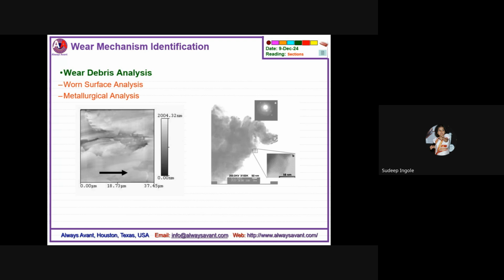The scale of this particular image on the left hand side is around 37 micron. You can see that 37 micron is a pretty small scale, and this image was taken by atomic force microscope, scanning a very small surface, whereas this also shows the vertical dimension, which is around 2 micron. If you see that, it looks very flat, but at very high resolution, as we mentioned very early in this presentation, there are still irregularities of the surface.